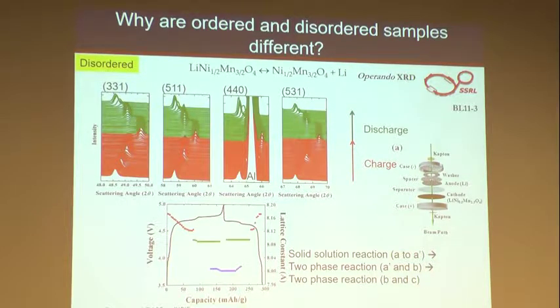It's a spinel structure, and the spinel structure is related to rock salt just by having occupancy of the tetrahedral sites. So you can push that atom in the tetrahedral site to an octahedral site and get a rock salt. And so if you put lithium in a titanate that is being used commercially, because it can push the lithium out, it doesn't need to rearrange the lattice as much, and so it's a very small change. It's less than 1% of the unit cell lattice, but it's still not zero. That's the closest I've seen.